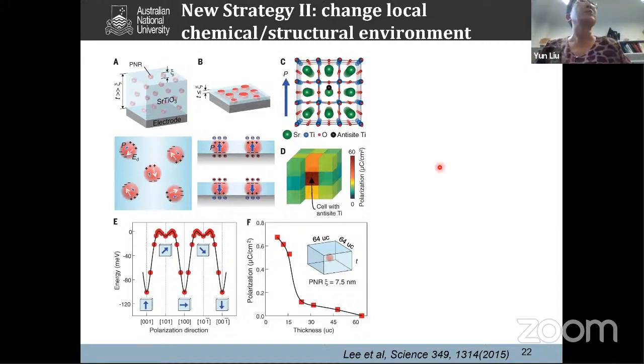So in their case, in a strontium titanate matrix, you have polar nanoregions. Strontium titanate is not ferroelectric, but you have polar nanoregions in these materials. If your strontium titanate dimension is much larger than the polar nanoregions, you wouldn't see the ferroelectric property, because the strontium titanate itself is not ferroelectric. But if you reduce the thickness of this thin film down to a comparable thickness with the polar nanoregion dimension, in that case, your polarization will go up. This is a curve you can see here. If your thin film thickness is at 60, you don't have a polarization, but gradually reduce the thickness, and you will see this polarization.